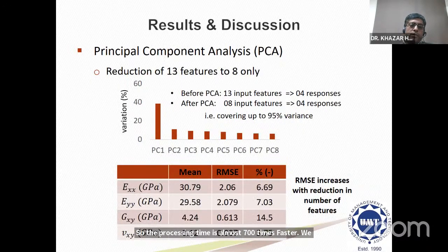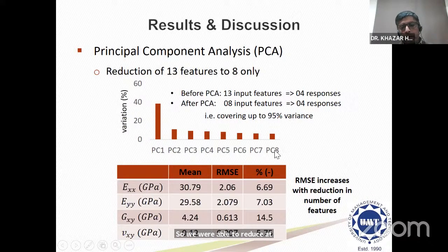We also performed principal component analysis, which is a technique through which we can convert a high dimensional problem into a low dimensional problem. So we were able to reduce 13 features to 8 features, but at the cost of some accuracy, still excluding in-plane shear modulus. For other in-plane mechanical properties, we have a reasonable agreement.